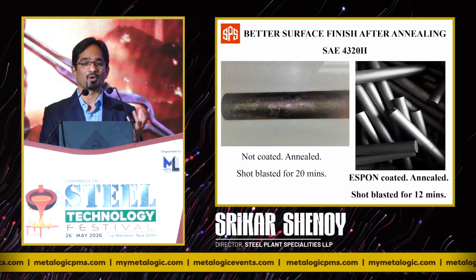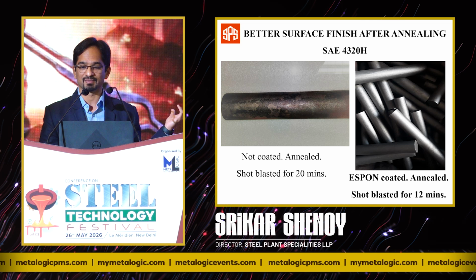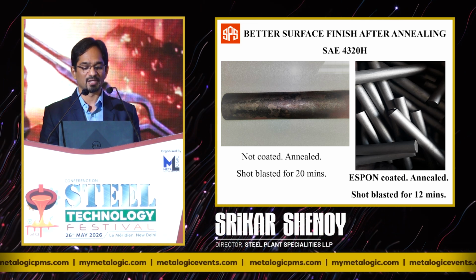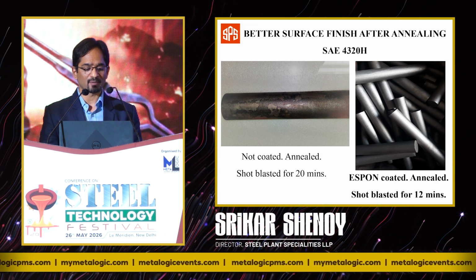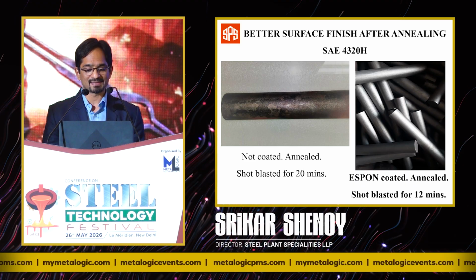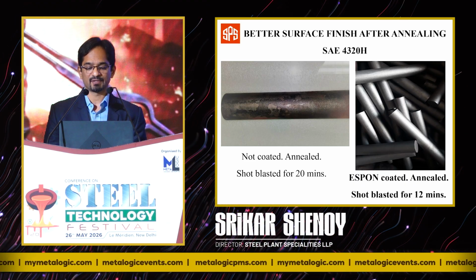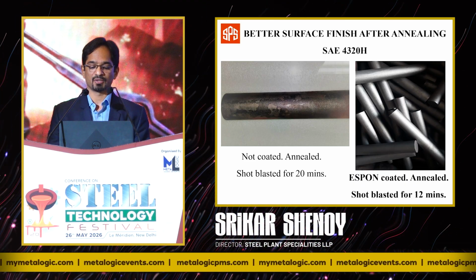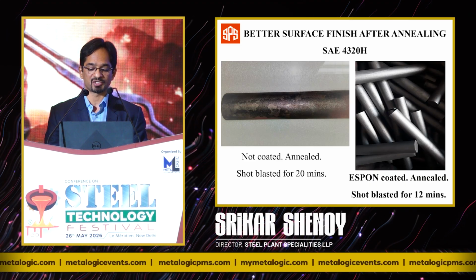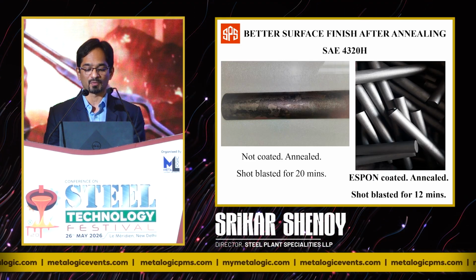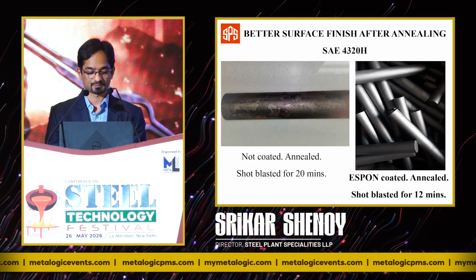But imagine making an automotive part using this component. I mean this billet. It would not look good. And shot blasting carried out for 20 minutes. At the same time, in the same furnace, if you use the metallurgical coatings, you can see a much better surface finish here, and shot blasting is reduced from 20 minutes to 12 minutes.